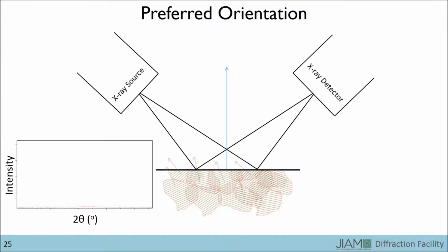When we collect pole figures, we align the source and detector at angles such that diffraction from a certain plane should occur. We then rotate the sample around two axes to determine qualitatively how many grains are aligned with the diffraction vector at each position. Let's go ahead and look at a real-life example.